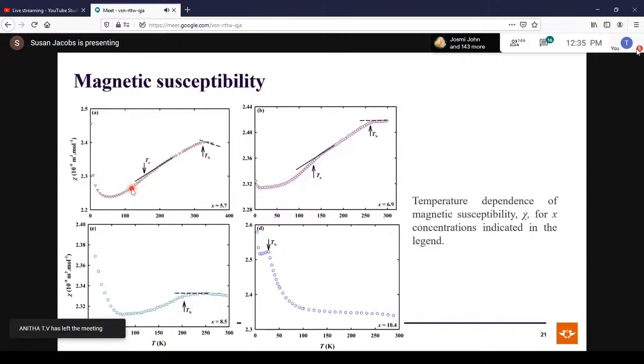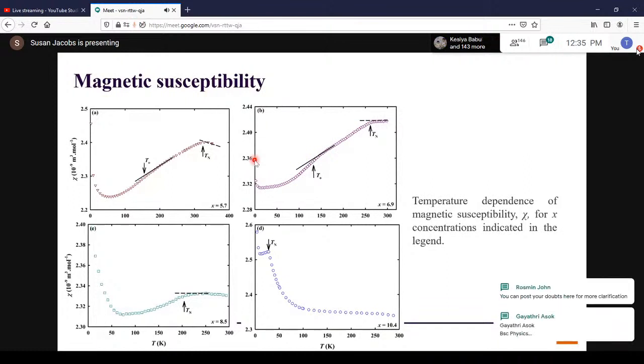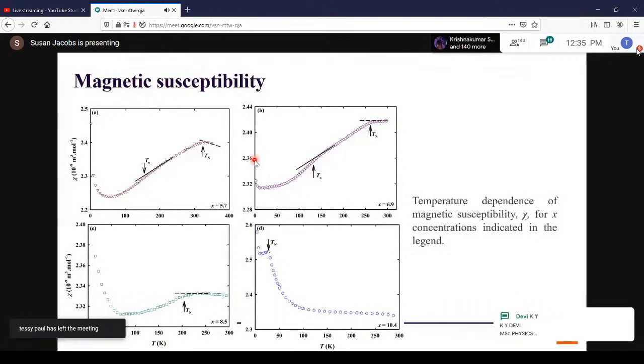So in all these curves, we see a deep valley as well as an upturn at low temperatures. And this has been reported to be a Curie tail, which arises from oxide impurities. And it makes sense because chromium has a high affinity for oxygen. So there is a good chance that our system also has an oxide.